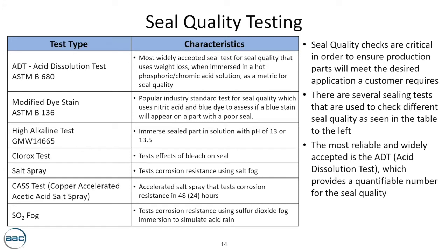The first one and the most widely accepted test is the acid dissolution test, where a part is immersed in a hot phosphoric chromic acid solution bath for a certain amount of time, and the weight of the part is noted before and after the immersion. This will tell us the amount of weight lost in the part, which will in turn tell us the quality of the seal. The second most popular test used in the industry is the modified dye stain test, which is done by using a certain strength of nitric acid and a blue dye. In this test, if a blue stain appears on a part after the test, you know that the seal quality is poor.